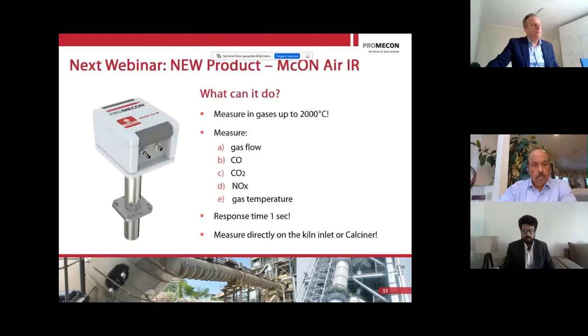You can see here, this is a new way of measuring gas flow. We have introduced this system a while ago in the steel industry because the steel plants need to measure gas temperatures up to 2000 degrees Celsius. So measurement right out of the converter or out of an electric arc furnace. They want to know the gas flow as well, but at 2000 degrees Celsius. So how can you put a sensor into 2000 degrees Celsius?